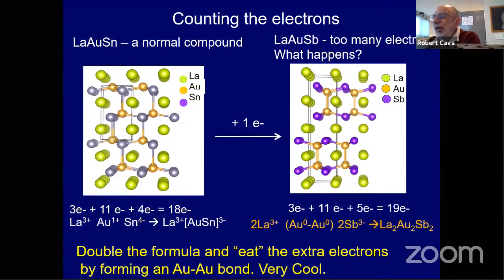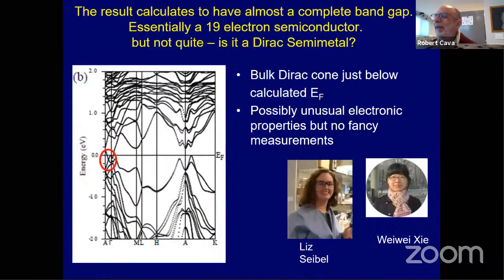So there's no charge transfer to or from the gold. And if I want to count these things, I end up taking this as a gold zero. And the thing that used to be a 19 electron compound becomes an 18 electron compound because the gold didn't donate anything to anybody. So it's just sitting there as gold metal. And it's a gold-gold bond for gold zero. And that is a very bizarre state of chemistry. And I think that got that paper in a nice chemistry journal.